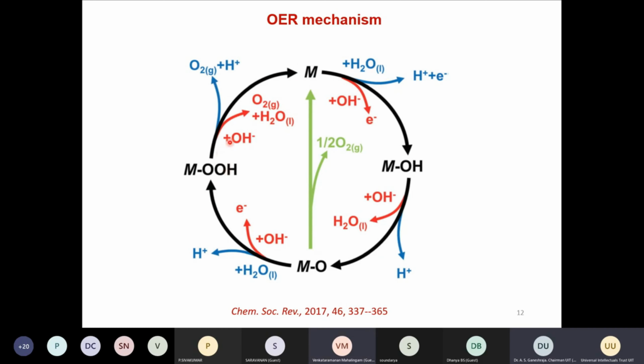But predominantly in this 4-electron process, the metal oxide to oxyhydroxide formation is well known. In most cases it's observed and has been proved as well. In some cases, with some catalysts, this metal oxide directly releases oxygen. But as you can see, this oxygen evolution mechanism involves a 4-electron proton transfer process. Therefore, the kinetics of each process is very intricate. The release of oxygen depends on all 4 steps, particularly the hydroxide to oxide and oxide to oxyhydroxide formation, which depends on the pH and various things. That is why this 4-electron process is a very challenging process.